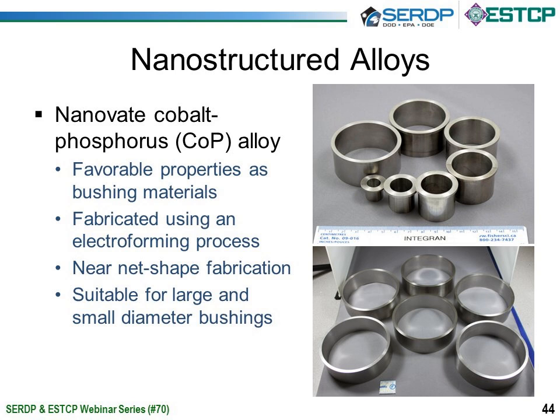Okay, next slide is nanostructured alloys. As I mentioned before, of all the nanomaterials evaluated in the SERDP program, the nano cobalt phosphorus alloys exhibited the most favorable properties as bushing materials. They can be fabricated using an electroform process, which is really a metal forming process by which parts are produced through electrode deposition on a model or a form, which is known industrially typically as a mandrel. Process is essentially electroplating, but with thick deposits formed.